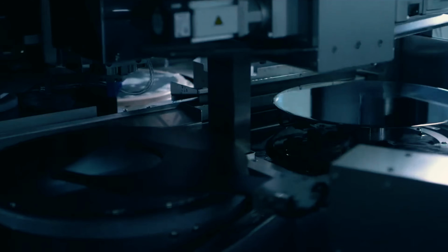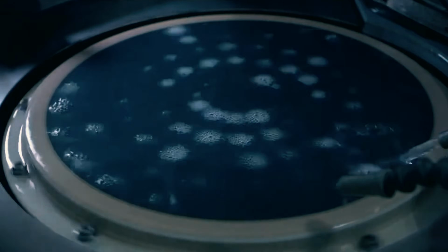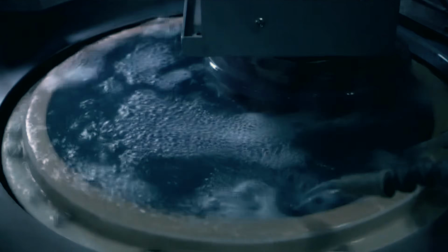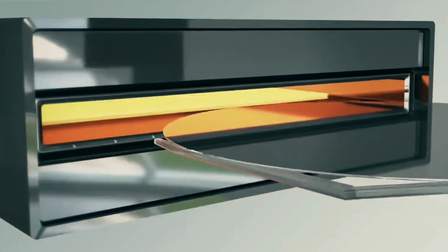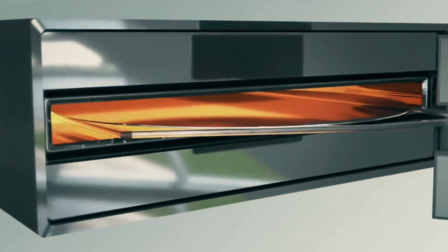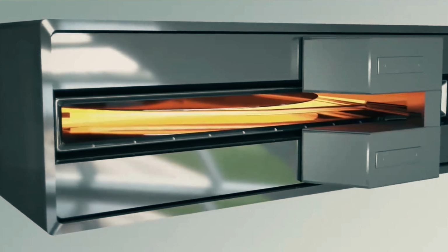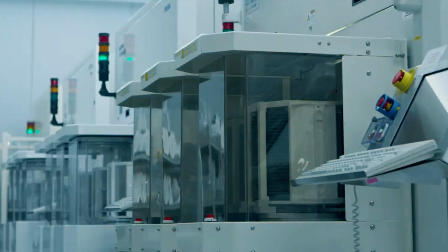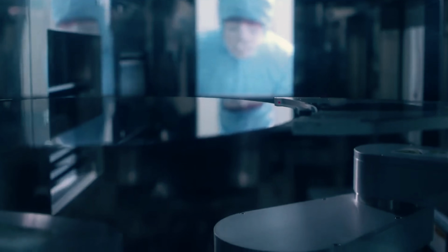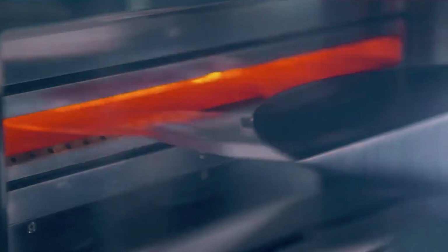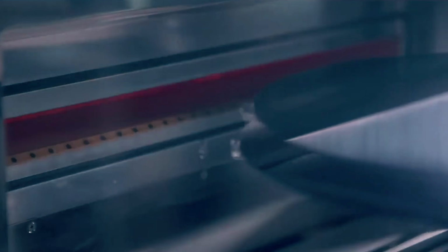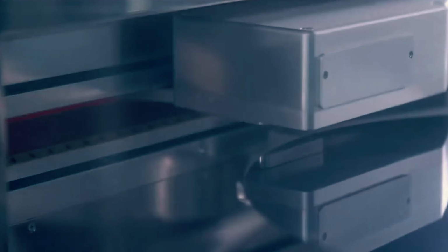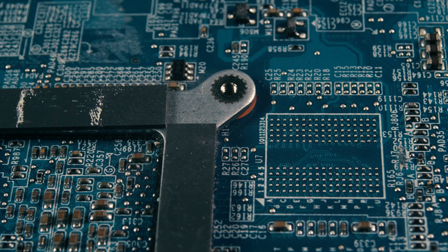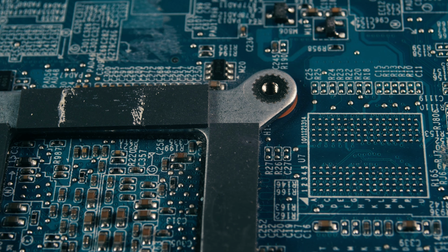Wherever light hits, the coating changes chemically, allowing unwanted material to be etched away with acids and plasma, layer after layer, sometimes over 100 layers stacked on a single wafer, each one aligned to the last with an accuracy measured in nanometers. In between, ions are blasted into precise regions to change how electricity behaves there, and metal wiring thinner than a strand of DNA is layered on top to connect it all. Millions of microscopic wires threading through a space you could cover with your thumb.